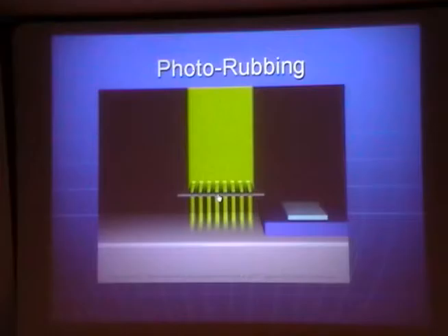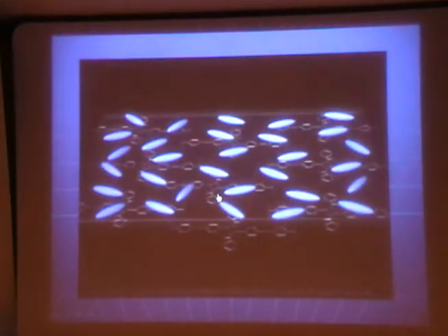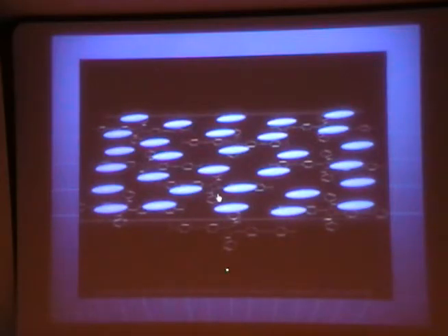So this is similar to the rubbing process, the classical rubbing process. That's where the name rubbing came from. Okay, and this again is what's happening. So interestingly, this single shot normal irradiation process gives the liquid crystal a pretilt angle.